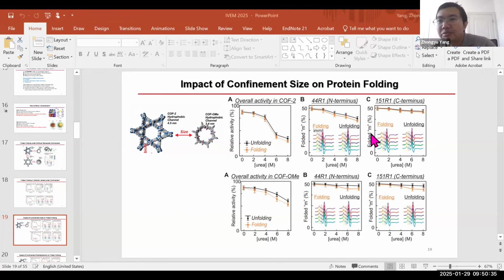But EPR can do time-resolved measurement. I actually have a stopped-flow system, so if I do stopped-flow and see how the signal changes, that will be interesting too. Because with the confinement, I would say the kinetics is going to be slower compared to liquid in buffer, where it's almost immediate: you drop some urea and the protein immediately unfolds. But urea needs time to diffuse into the MOF, and the protein inside the MOF needs time, the water, the entropy of water.